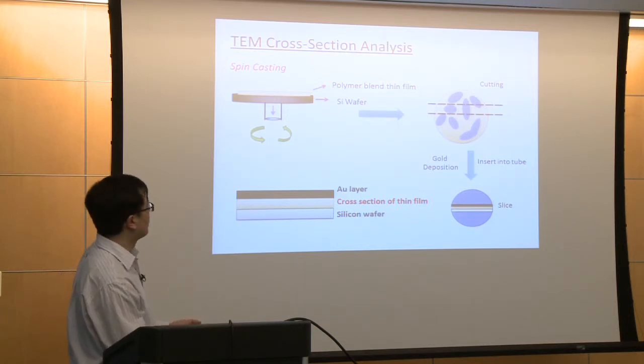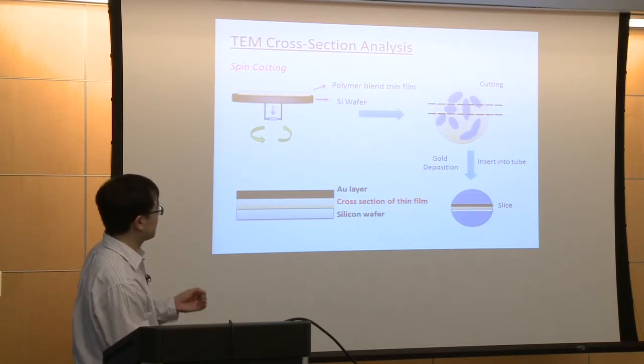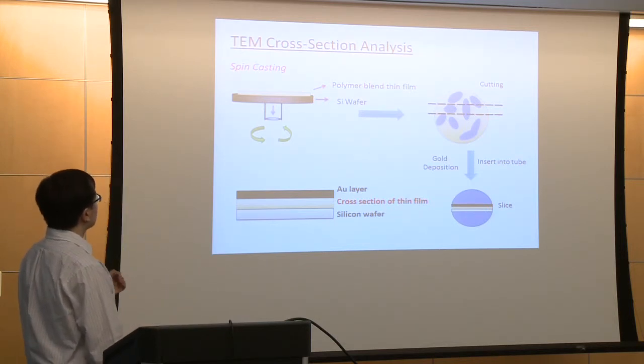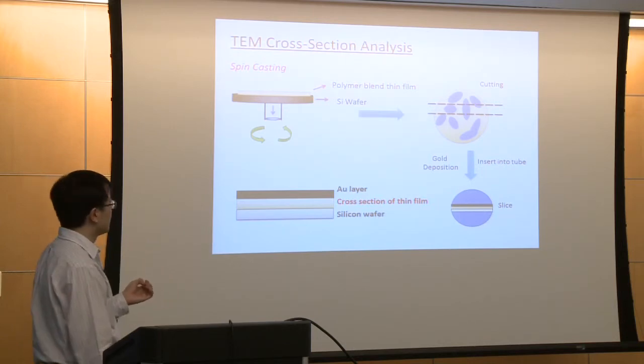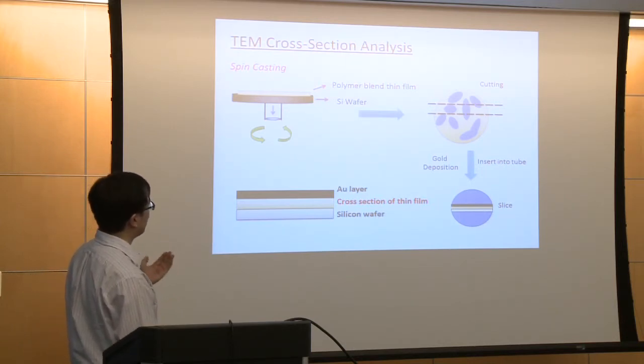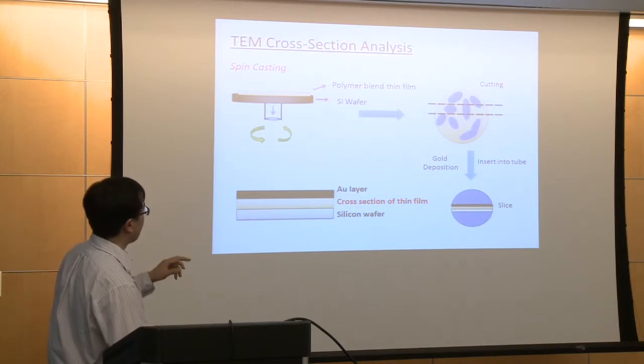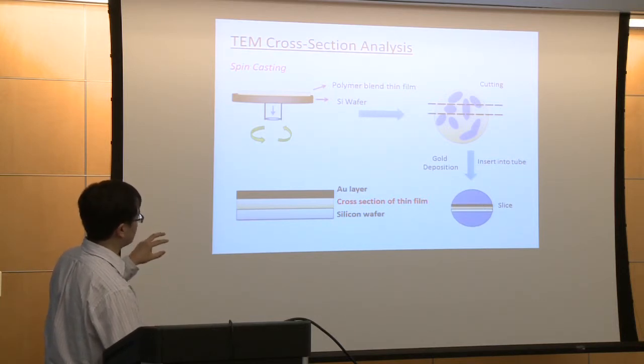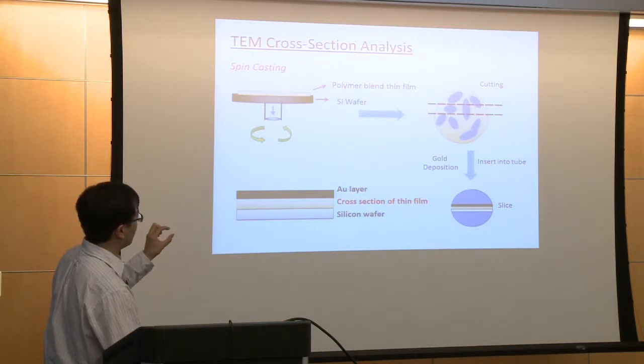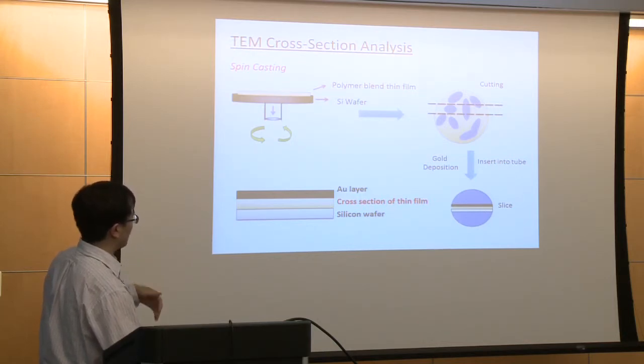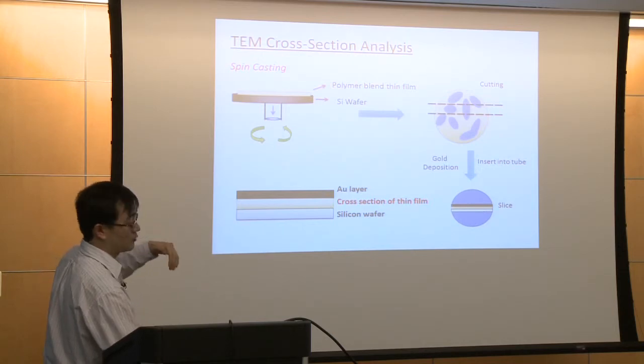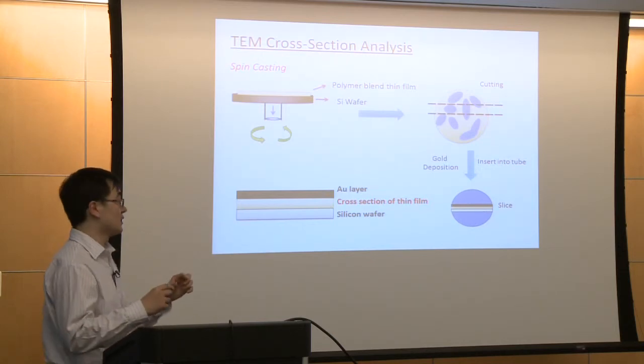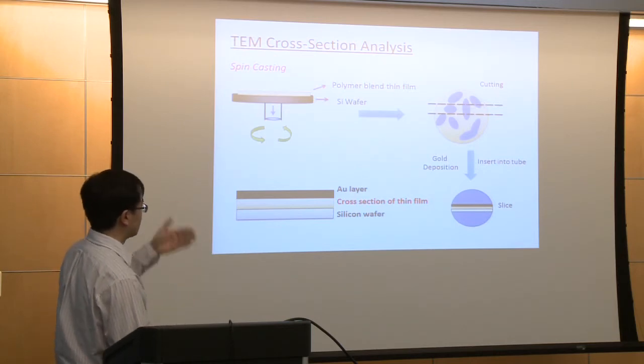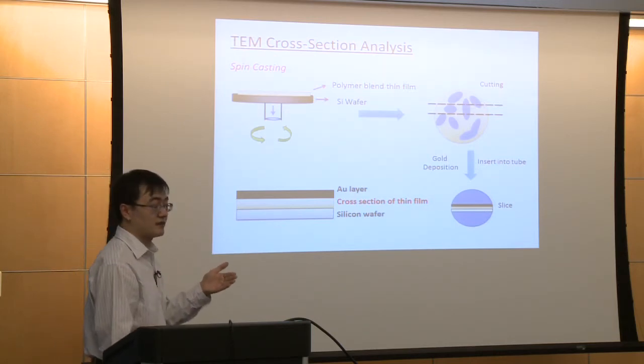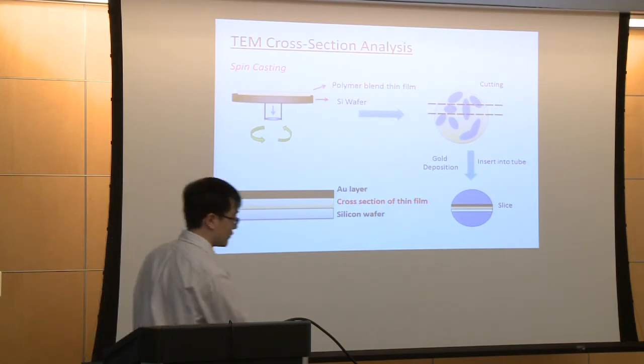But how can we prove the column structure? We need to take a look at the cross-section of the thin film, so we use TEM cross-section analysis. The method is we spin cast our film on the silicon wafer, then we cut a small piece of the silicon wafer out, including the domain we want to look at. Then we deposit gold on the top just for good contrast, and then we insert that piece into the tube and cut a slice out. In this way, we can take a look at the cross-section of our film.